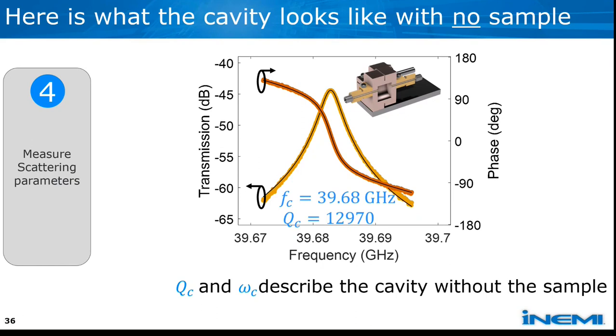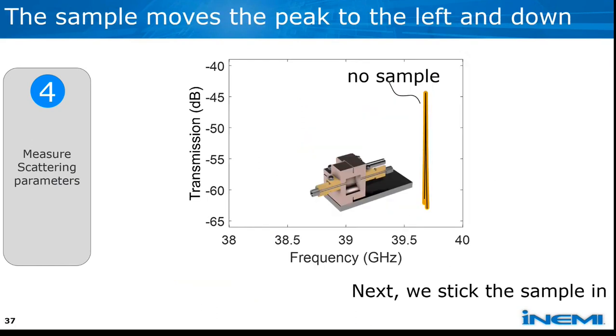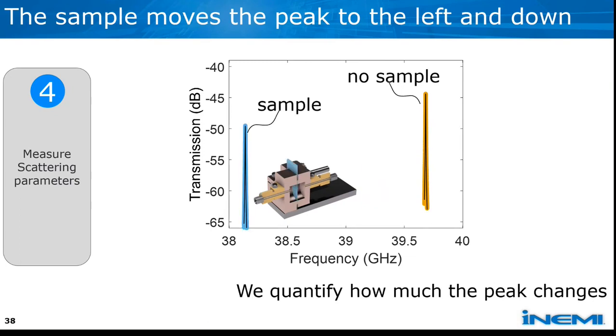Go ahead, next slide. So let's zoom out here. We're going to zoom out and we're going to look at the cavity. You can see that it's a very, very sharp peak without the sample. Go ahead, next slide. Once you introduce the sample, the peak moves to the left and down. That's because you're kind of like loading the capacitance in the cavity, and it's kind of like an LC circuit. So as you increase the capacitance, that's inversely related to the resonance frequency, and so it shifts down. So we measure how much it shifts down. Go ahead, next slide.